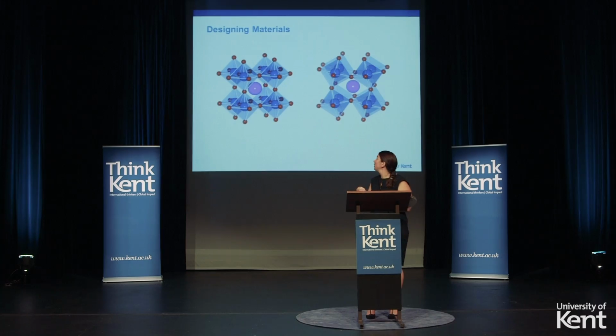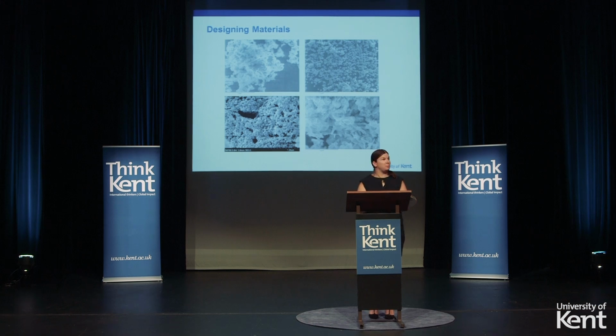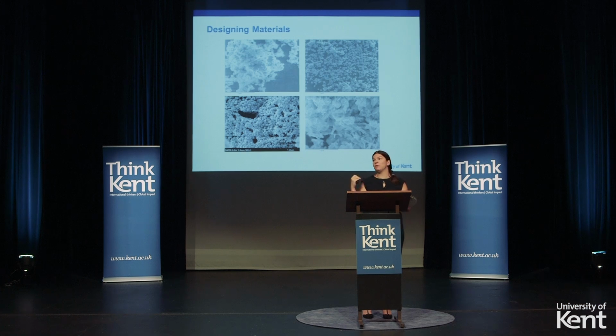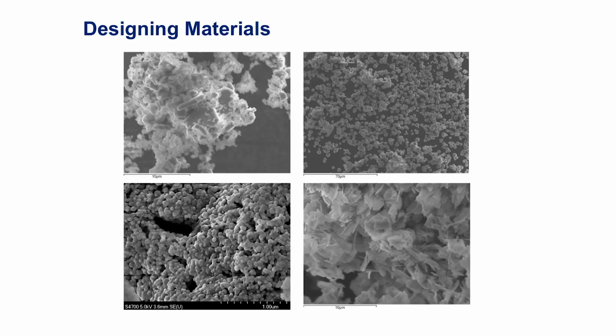However, if we now change out the pink ion in the middle there for an ion that has a bigger ionic radii, it now doesn't fit in this channel very well. As a result, what happens is these octahedral units buckle out to make room for this cation to fit, and we start to get interesting properties. Things like electronic properties that are not shown in the cubic version. One other method that we have at our disposal to change properties is by changing morphology. Morphology describes the shape or the appearance of the actual particle, so not the structure, the actual particle of the material, a bigger three-dimensional structure. If we change the morphology, we start to change the behavior of our materials.